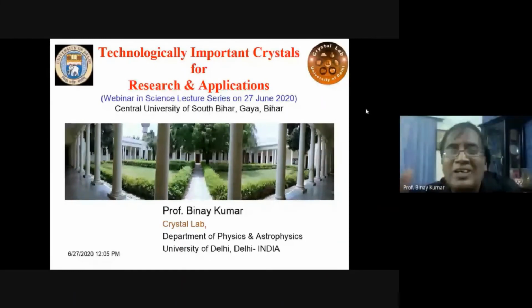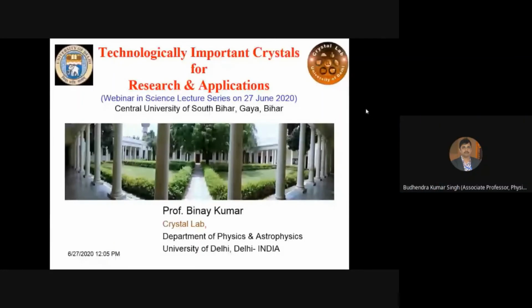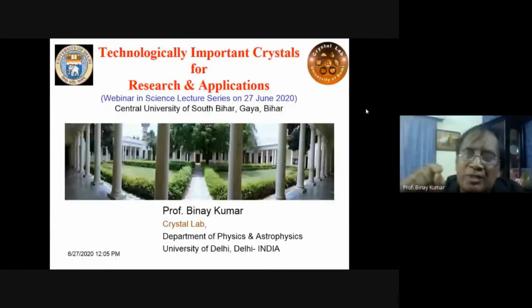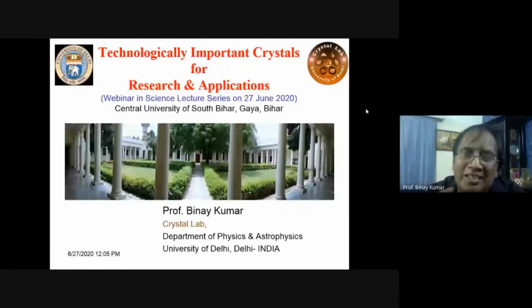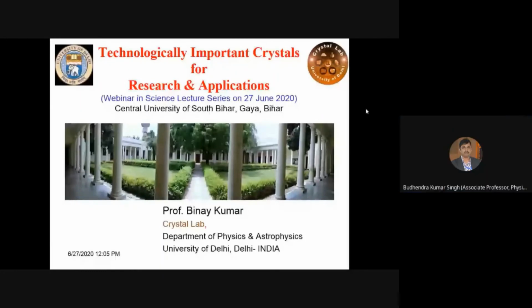This is one. Second, if the crystals are growing through spiral growth, at the center of this spiral, from where the nucleation starts, a dislocation line is terminating, and that point at the center of the spiral is used to develop the crystal through the spiral. In this sense, I'm saying that defects or impurities are helpful in growing the crystal.